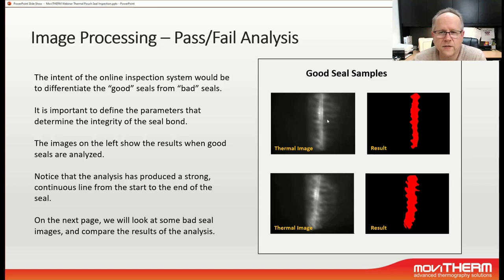We have tested this by a destructive test by pulling several seals apart and making sure that the weld is strong and there's no gaps in the seal. And our image processing creates actually a threshold for the energy that needs to be in the seal to determine that the seal is strong. And this is represented by this red blob that we have here.